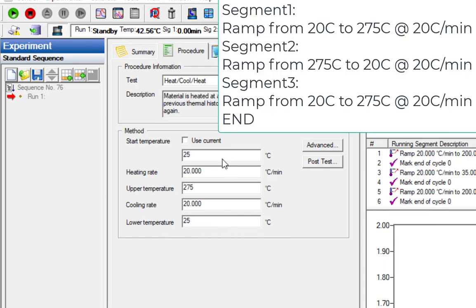So what this tells us is we're going to start at 25. We're going to heat at 20 C a minute to 275. We're going to cool at 20 C a minute back down to 25. And then what it doesn't show, because it uses the same parameters for the second heat, is heating again from 25 to 275 at 20 C a minute again.